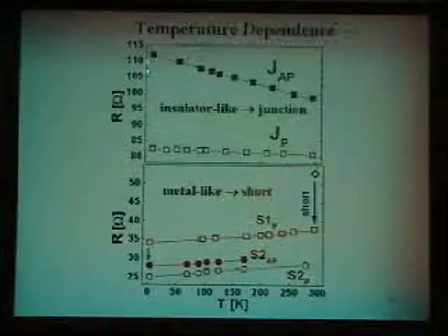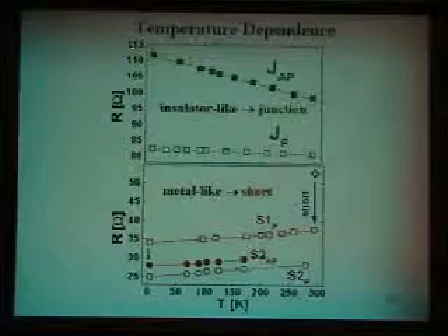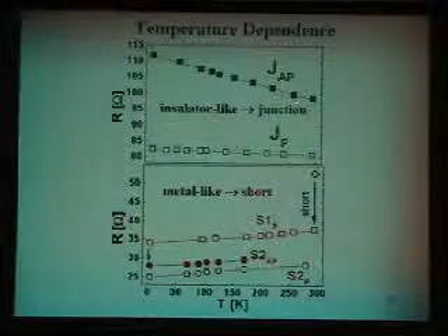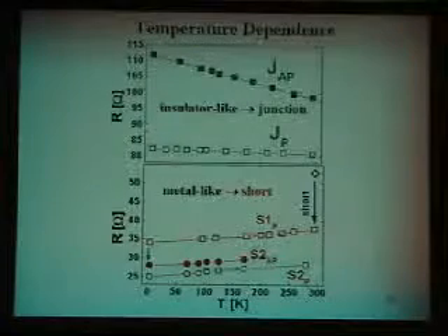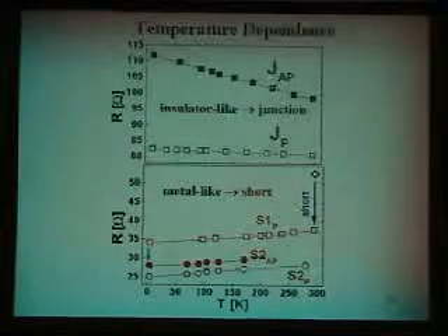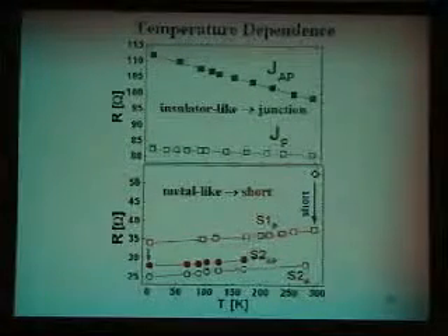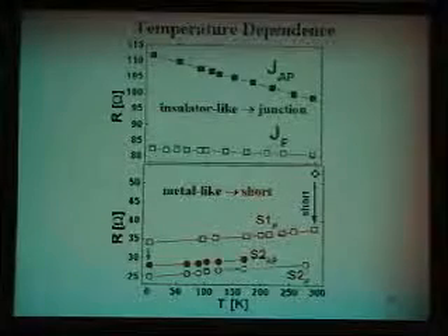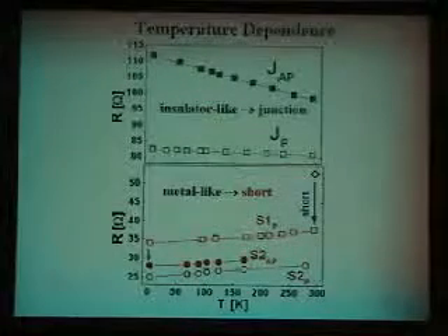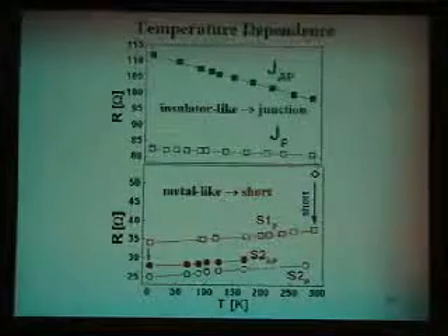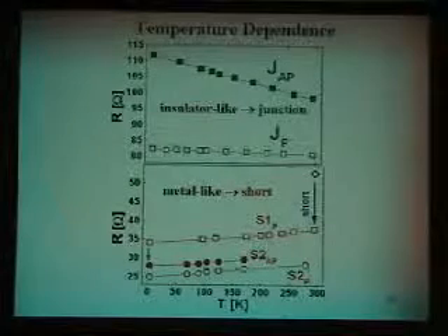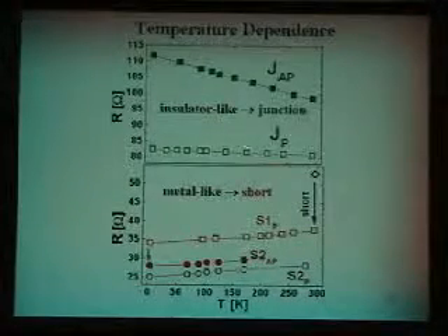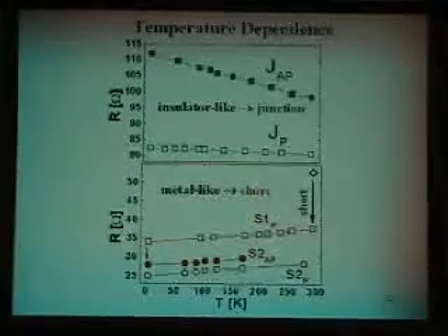So here is the temperature dependence. There is the resistance as a function of temperature. There is the virgin junction. See, there it is. Okay, so this is the parallel configuration, when the two spins are pointing like this in the junction, and the anti-parallel direction. Those are the two green curves there. So that's a good junction characteristic for the parallel and the anti-parallel direction. The dependence as a function of temperature is insulating-like. It looks like a good tunnel junction.